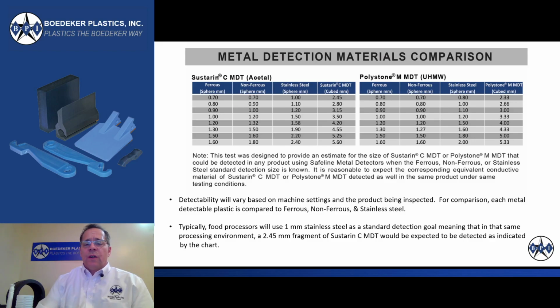And the way this worked was we first set up the detection systems based on a known metal or stainless steel standard. And then once we set up to the stainless steel standard, we ran the various ferrous and non-ferrous metals and plastics through and saw how small we could detect those different materials with the same setup. So to explain the first line here, you notice on the left-hand side we have a stainless steel sphere of 1 millimeter in size, and we set the system up to be able to detect that 1 millimeter sphere.